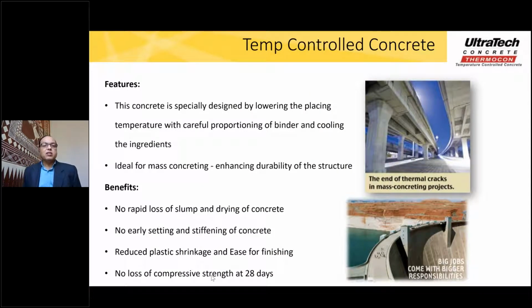Now, why should we control the temperature? It is from the point of view of thermal cracks. Whenever concrete is used for mass concrete projects, the heat of hydration would be so high that huge cracks develop in the concrete. Therefore, in such projects, whatever the strength of concrete that you make, whether it is M20 or 30 or M50, in addition to that, you should also ensure that the temperature of concrete is quite low.